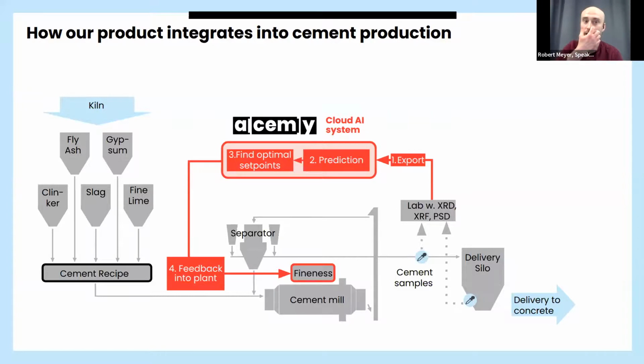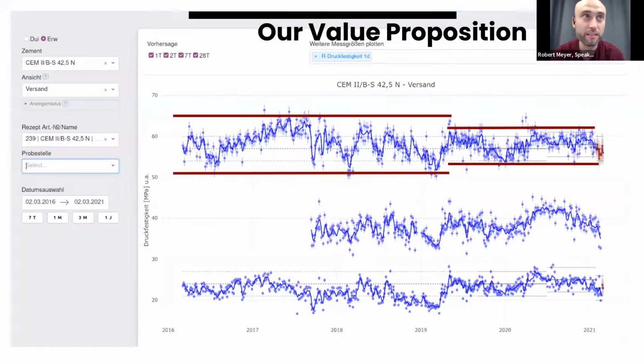And here's an example of how that turns out with real data. What you see here is data over 5 years. Each of these blue lines corresponds to a different strength. Down here is the 2-day strength, here's the 7-day strength.